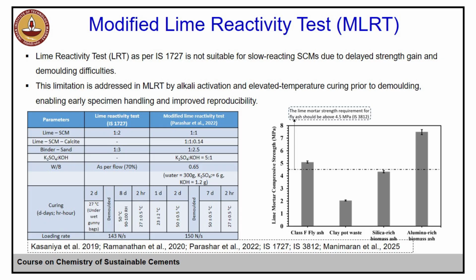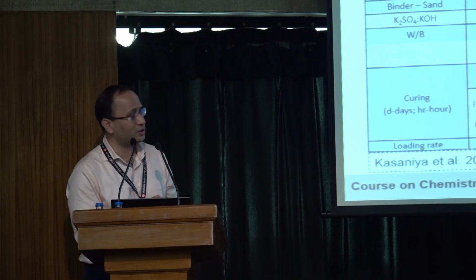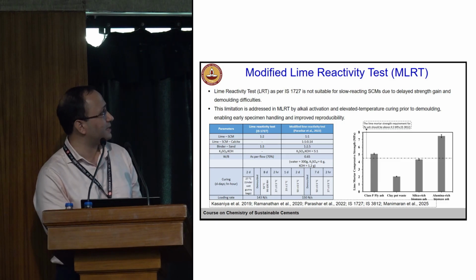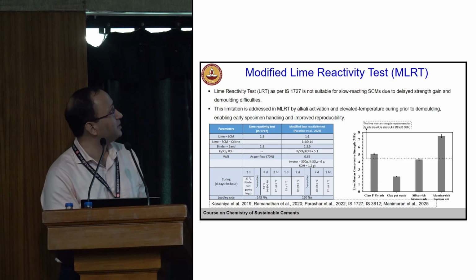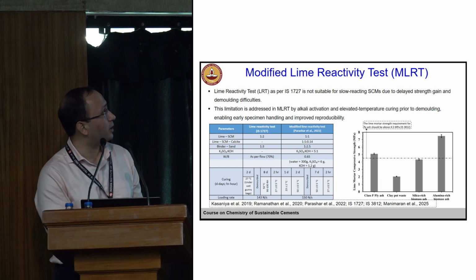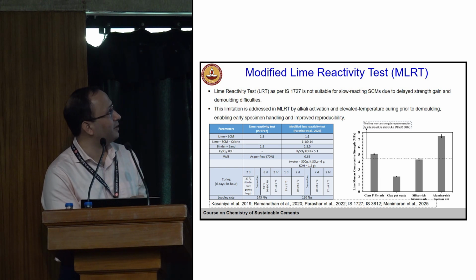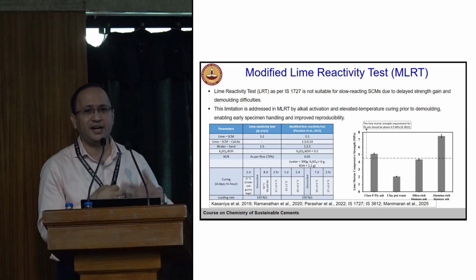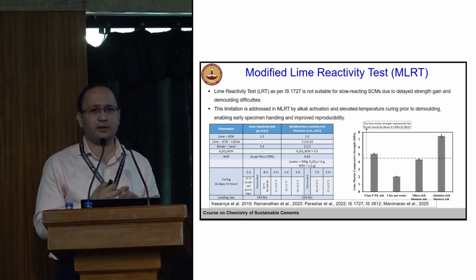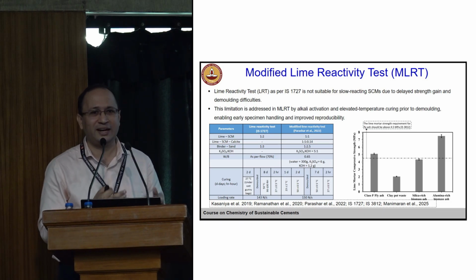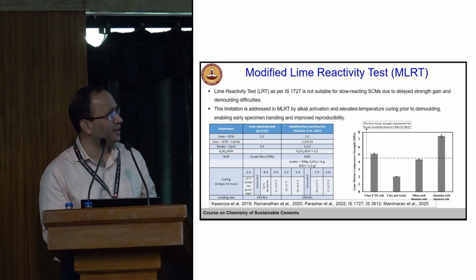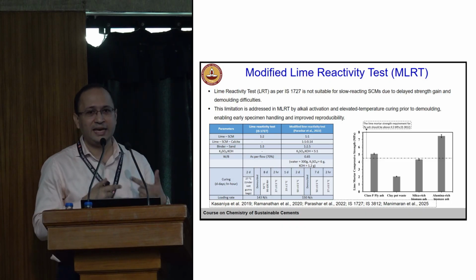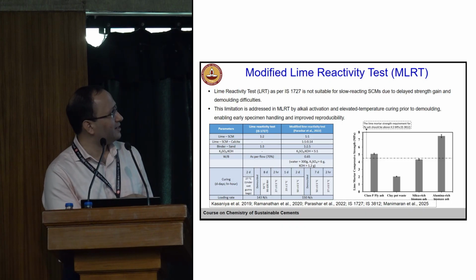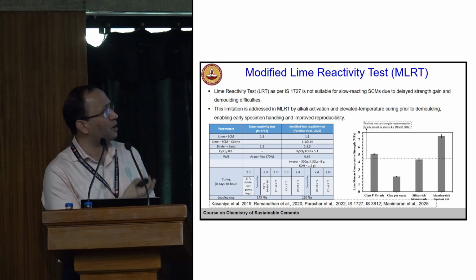Finally, the modified lime reactivity test. Again, sometimes it becomes difficult to demold the samples because of the slow strength development. So what we change is we slightly change the temperature, so the limitation is addressed by MLRT by alkali activation. When you add a little bit more alkalis, even the SCMs which are not that reactive will react a little bit faster, and with the elevated temperature we also enhance the reaction kinetics. So that's the change, and that also is one way to evaluate the SCM.